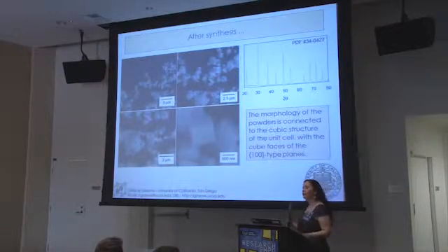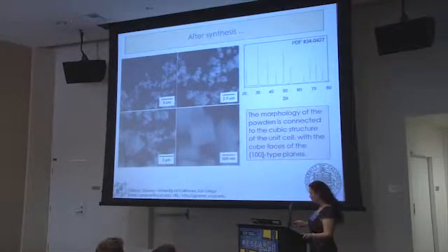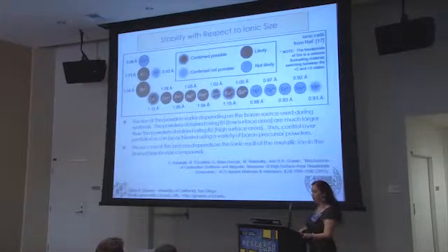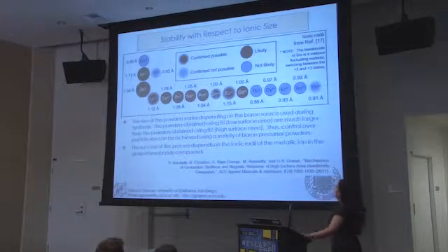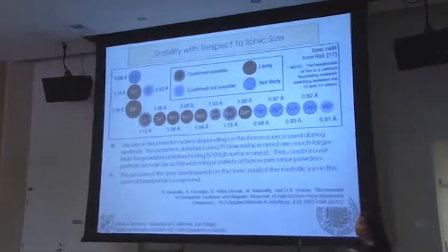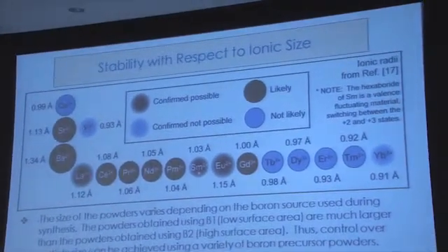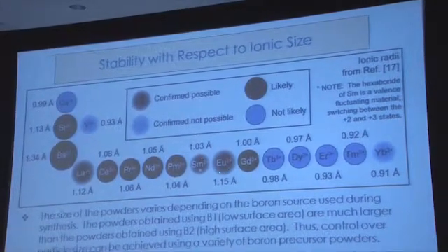And so my lab really focuses a lot on making nanocubes, controlled morphology, controlled size, and also other morphologies that we're interested in. That is a big effort that we've been working on. And lanthanum was just one example. Lanthanum hexaboride was the one that happens to be a conductor. But if you prepare samarium, for example, or europium, because they're +2 charged, you're going to end up with a semiconductor. And these ones are also ones that we've produced.